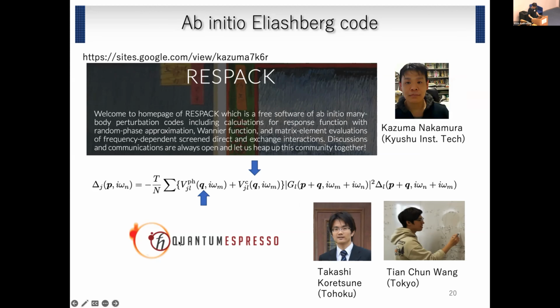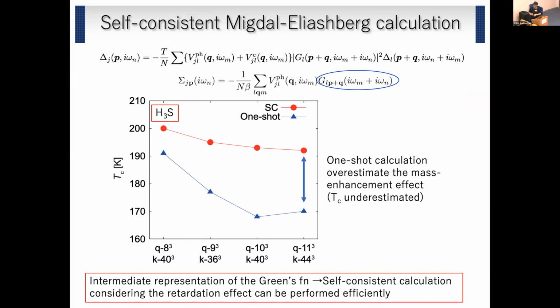And the advantage of this approach is that we can solve the Eliashberg equation self-consistently. Self-consistent means that in this Eliashberg equation, this is the Green's function, and the Green's function has a self-energy, and we consider the self-energy due to the electron-phonon coupling. And we solve this equation self-consistently, and we use this sigma in this Green's function. And this self-consistency is sometimes very important